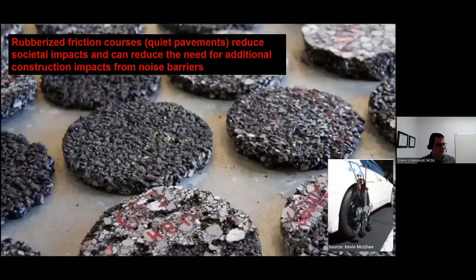Again, not in as much favor as it was 20 years ago, but there are also examples of using rubberized friction course. These are usually open graded friction courses that help to cut down on pavement noise. In the city of Phoenix, where I used to live, the freeways in that city were all covered. This was probably 15 years ago or more, with a surface of about 25 millimeters of rubberized friction course. And this cut down on the noise considerably. If you've ever been to the city of Phoenix, you know that the homes are usually built right up against the freeway. Those were topped with Portland cement concrete, and then this rubberized surface course was placed on top and cut down on the noise significantly. So much so that the citizens actually voted to increase their taxes to pay for more widespread usage of these materials.